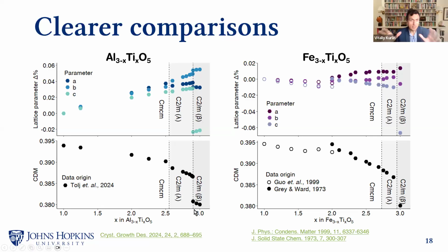So you mean that atoms are simply located differently? Yeah, but they're not speaking about atoms. It's only lattice parameters here. This is true, that we are speaking about the lattice parameters, but the reason that they have changed is because there is now a lower energy configuration for the atoms. Or you can think of it as the packing of the atoms, because we're basically stuffing more titanium atoms into this unit cell. Once we have enough titanium atoms here, they're no longer wanting to configure themselves in an orthorhombic or nearly orthorhombic structure. They have to be very monoclinic in order to minimize the empty space in the unit cell.